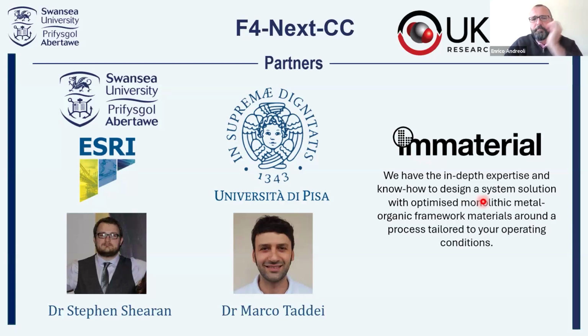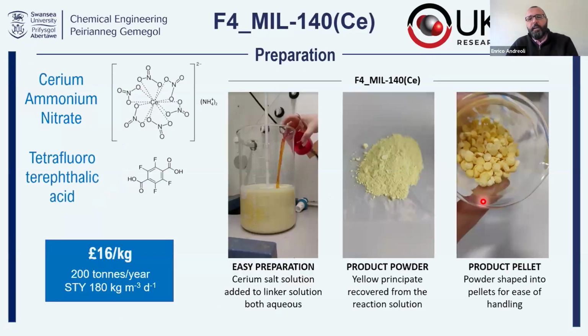who collaborated with us. So what we did, again, very quickly, was to produce this MOF, this yellow powder here. So it's not really very complicated. It's a powder. This powder can capture CO2. Obviously, it is more complex than that. There are many factors to consider, but I try to keep it simple. The powder can also be shaped into pellets, and it can be made very easily in water using relatively cheap chemicals. So we proved in the laboratory that what in engineering terms we call space-time yield could be at a particular value that was of interest for industrial scale-up of production of this material.